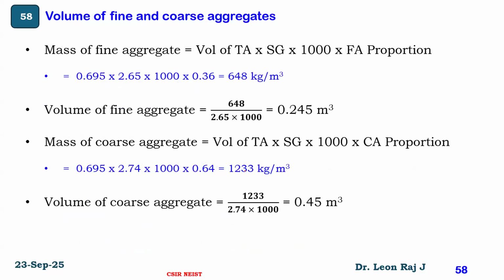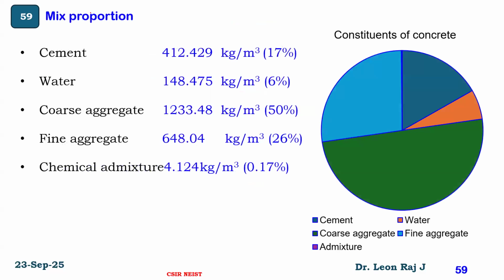That is, 64% of the total aggregate is coarse aggregate, and 36% of the total aggregate is fine aggregate. Then the mass of the fine aggregate, mass of the coarse aggregate, and then the volume of the fine aggregate and volume of the coarse aggregate are calculated. So the final outcome is this: cement 412 kilogram per meter cube, water 148 kilogram per meter cube, coarse aggregate 1233 kilogram per meter cube, fine aggregate 648 kilogram per meter cube, chemical admixture 1%, that is 4.124 kilogram per meter cube.